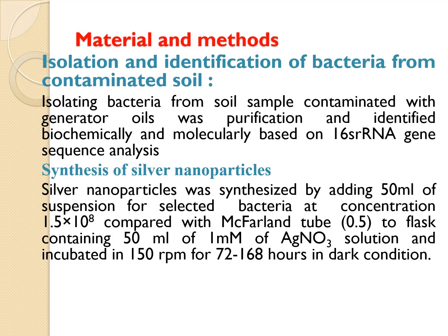Materials and methods. Bacteria were isolated from a soil sample contaminated with generator oil, purified, and identified biochemically and molecularly based on 16S rRNA gene sequence analysis. Silver nanoparticles were synthesized by adding 50 ml of suspension of the selected bacteria in this study to a flask containing 50 ml of 1 millimolar AgNO3 solution and incubated in dark conditions.